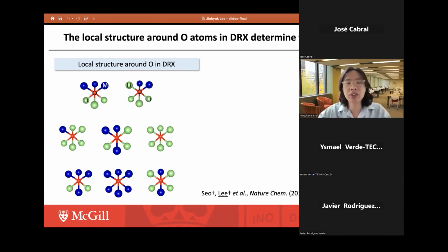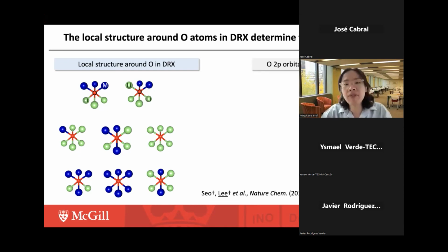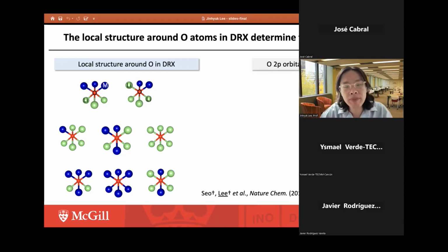Because the local structure is different, resulting in different ligand fields, okay? But now, if you look at this configuration, we found that there are too many, right? It's difficult to understand. So in this paper, to simplify this, we boil them down into 2 possible scenarios from the perspective of the oxygen 2p orbitals.